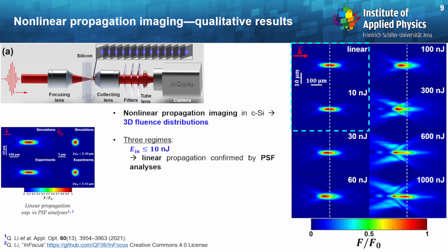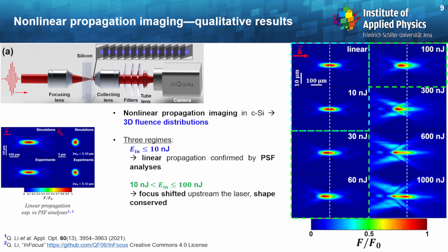The first one is for very low pulse energies, lower than typically 10 nanojoule. Well, we are clearly in the linear regime as confirmed by point spread function analysis. We carried out those simulations with the following open access and open source model developed by my colleague Qingfeng. So if you want to make such vectorial simulations, just feel free to check this code. All right, then if we increase the input pulse energy to something between 10 and 100 nanojoule, then one can see that the focus unambiguously shifts upstream towards the laser as a consequence of the Kerr effect. However, in that case, the overall shape of the focal region is conserved.